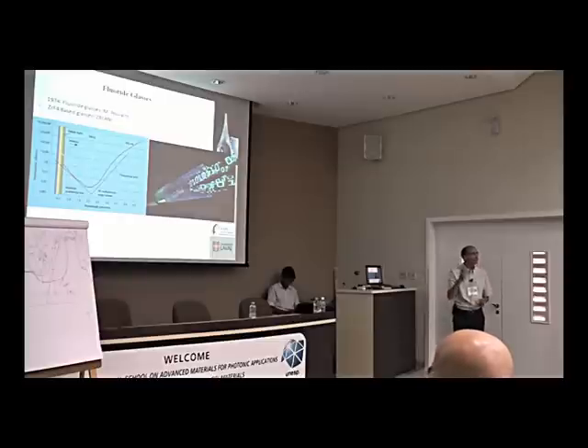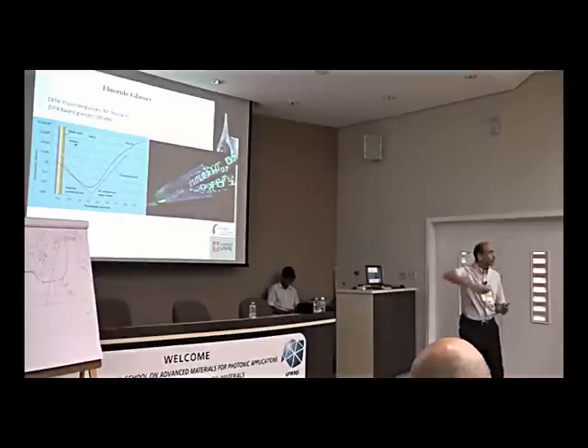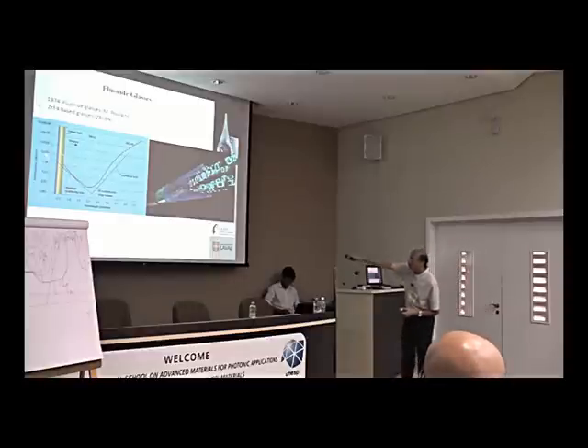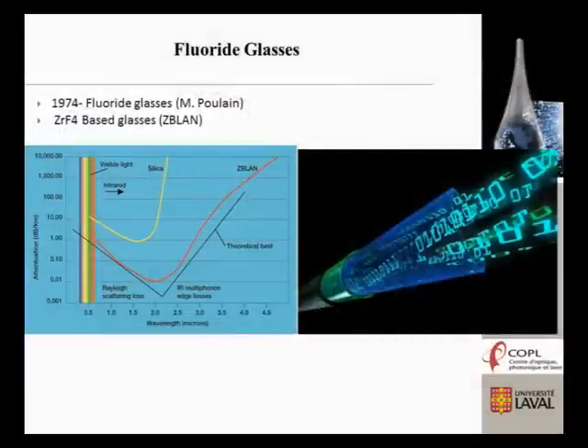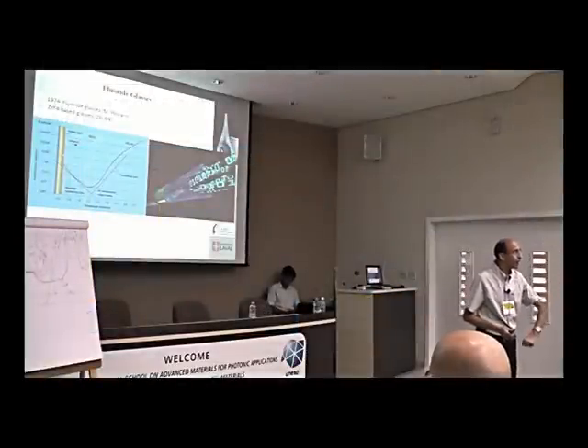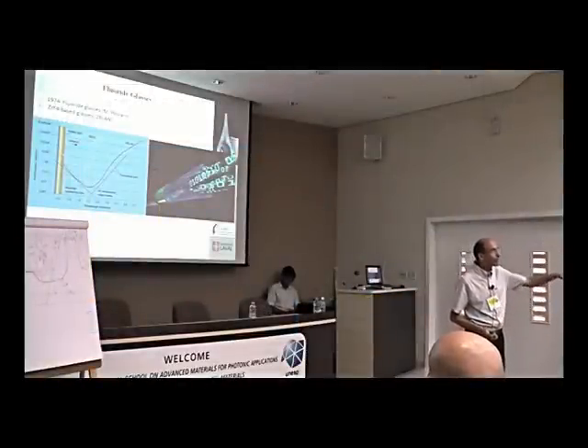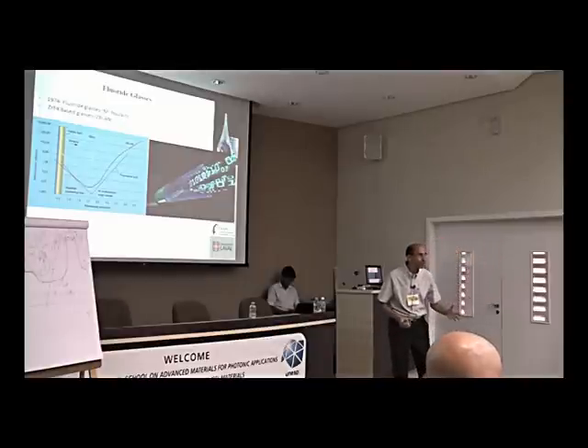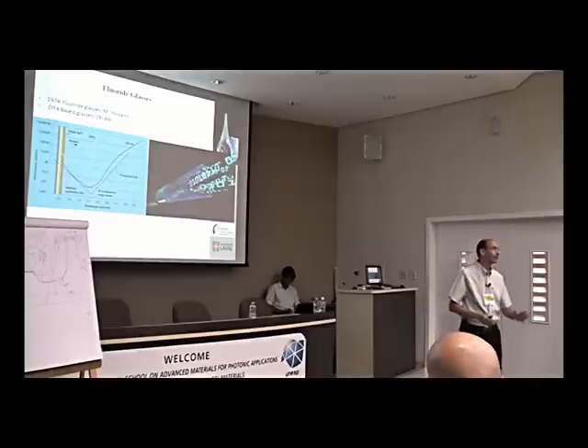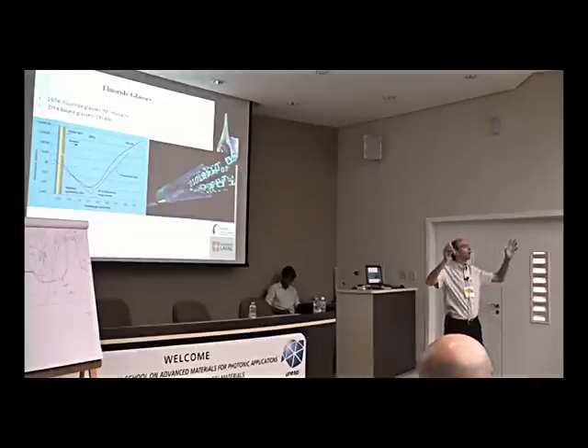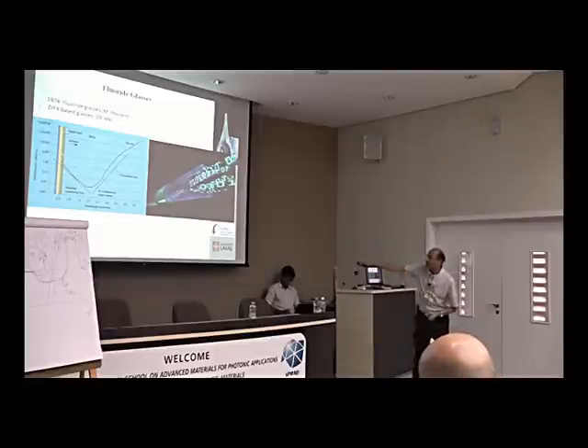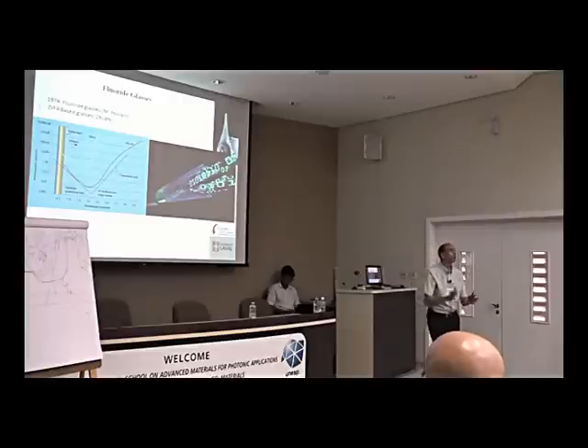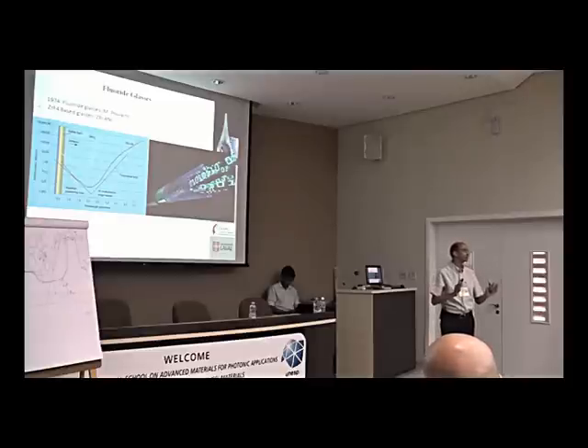And the dream at that time was, because they made the theoretical predictions, and they showed that with this fluoride glass we would be able to reach almost 10 to the minus 3 dB per kilometer, around 2.4 micron. Everybody was excited and said, okay, we'll change all the communication network systems. At that time, almost 90% of the installation was made in silica. How would we change all the silica using the fluoride glasses? Just after 2 or 4 years, the dream of everybody changed, because we were unable to reach this theoretical value. The experimental value today is around 10 dB per kilometer at 2.4.